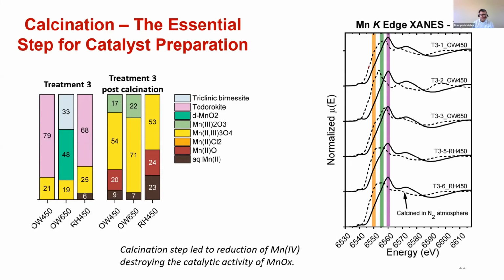And then it occurred to us that we should have known from the get-go that these biochars are actually not inert material. They have a lot of carbon moieties like quinones, which are electron shuttles. They also have reduced sulfur groups, which we know because we have measured those, and I'll show you in one of the next slides. And in addition to those, we definitely also have iron oxides embedded in it, mixed iron oxides. So they can be quite a strong reductant, and when you heat them up in the calcination step, these electron shuttles actually become more active.